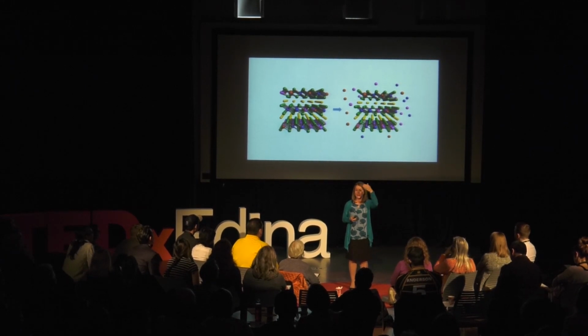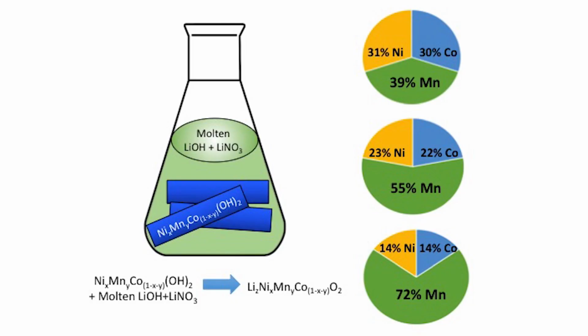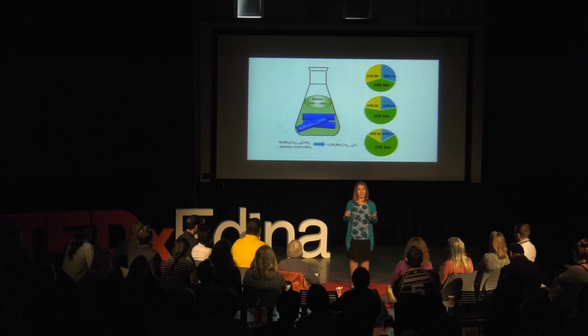We'd vary the amount of nickel, manganese, and cobalt, because we knew the nickel and the cobalt were the bad actors. We can decrease the amount of nickel and cobalt. We can't eliminate it completely and still get all the advantages of nanoscale NMC, but we designed a series of nanoscale NMC formulations using chemical reactions, like the one you see here, where we increased the amount of manganese at the expense of the nickel and cobalt. And then we did the same experiments with our Shewanella to see if our redesign had worked.